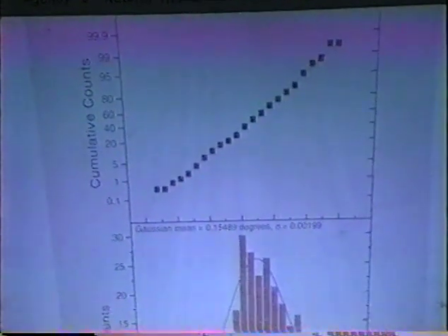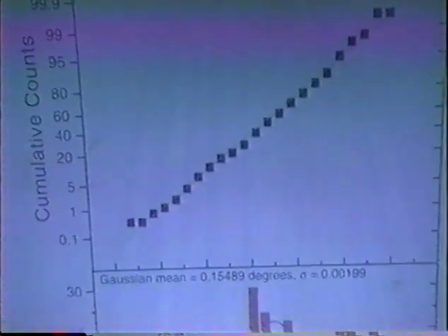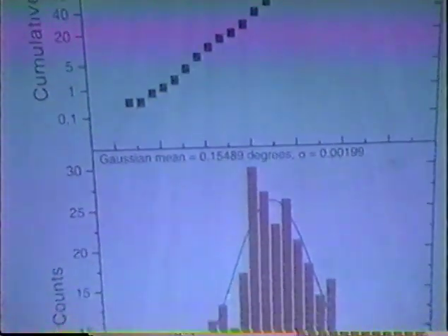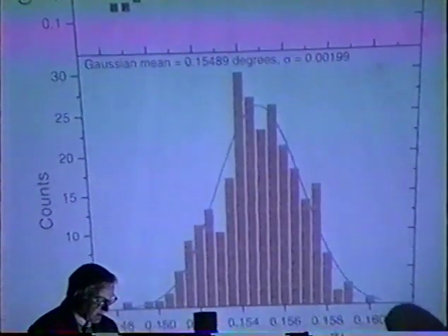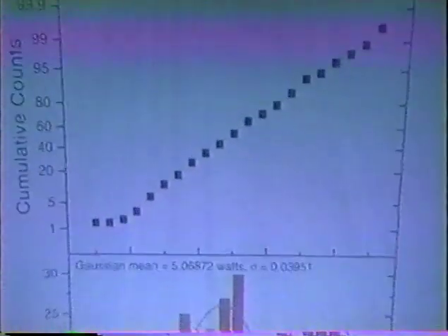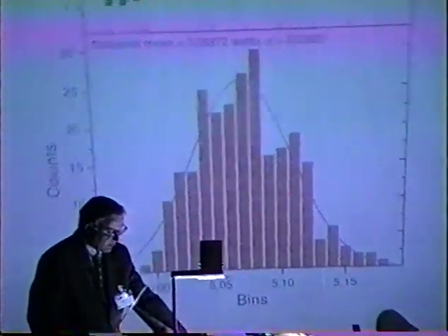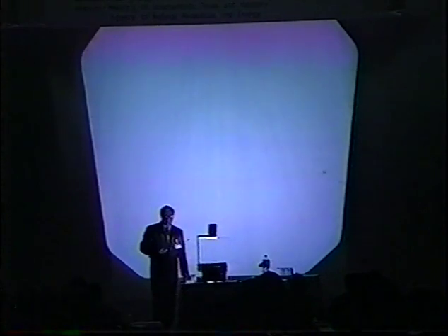You can then do a histogram analysis, which will give you the mean and the standard deviation of both the temperature difference and the power input. So you can see that we have a standard deviation, for instance, on the power of 0.03 out of 5.06 watts input. So you do that for every point. You then, point by point, build those three calibration curves, and then you run various experiments.